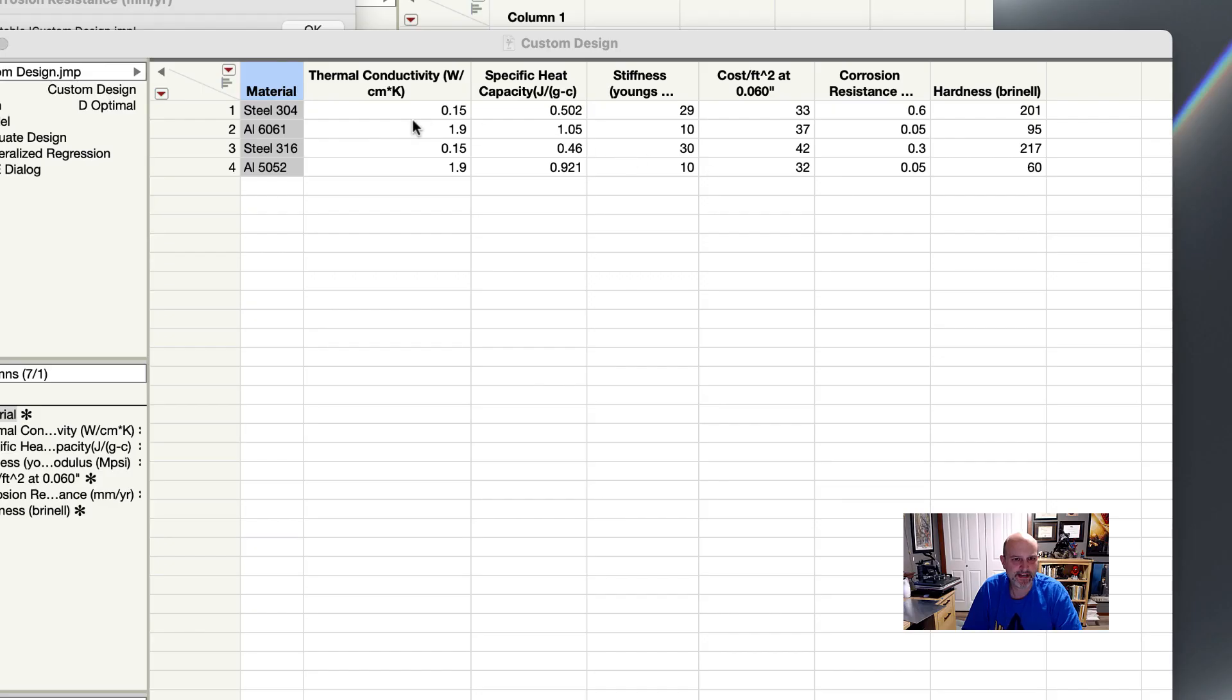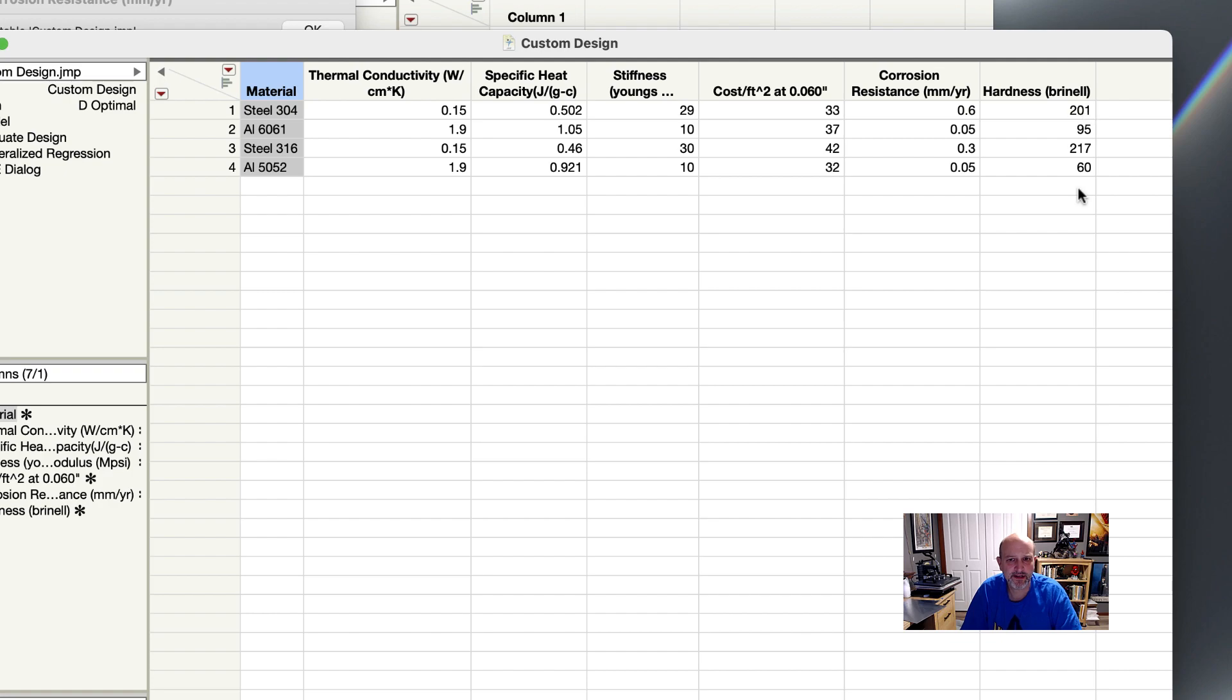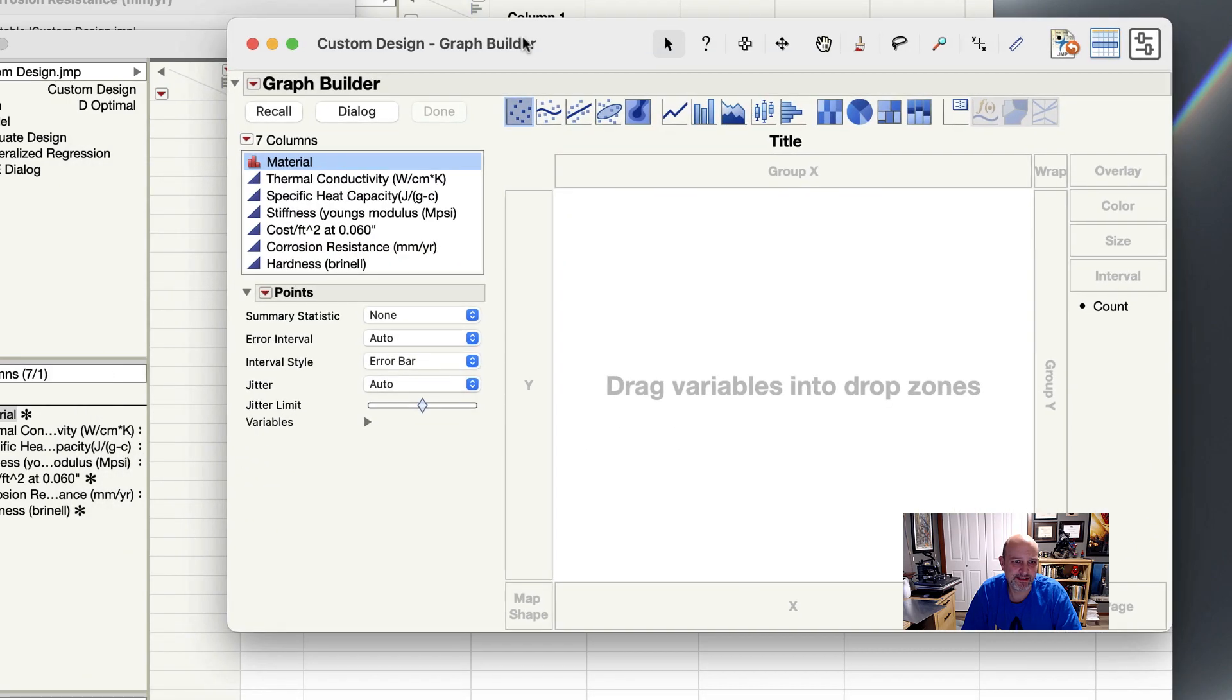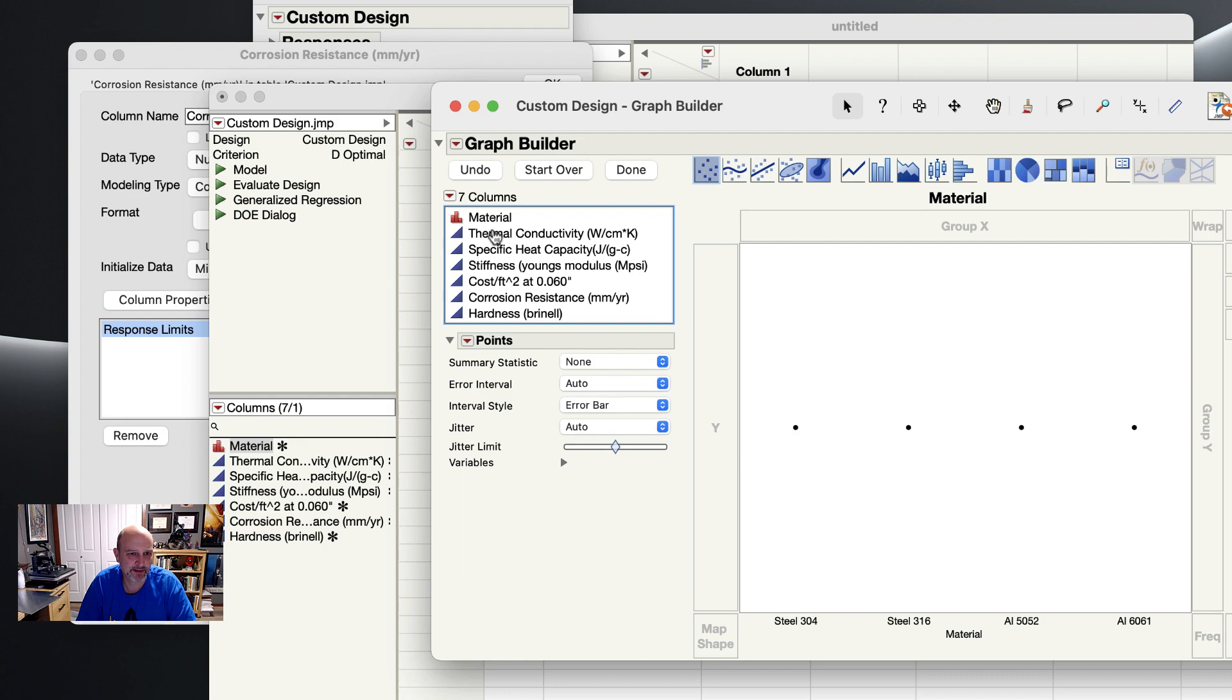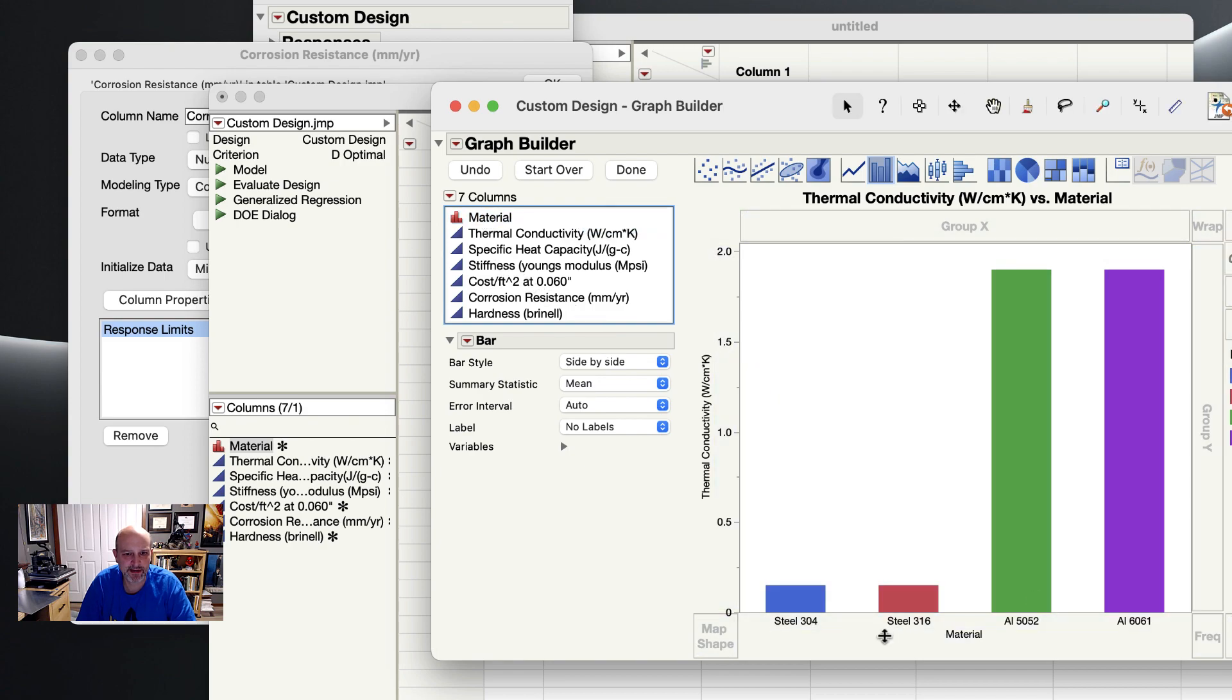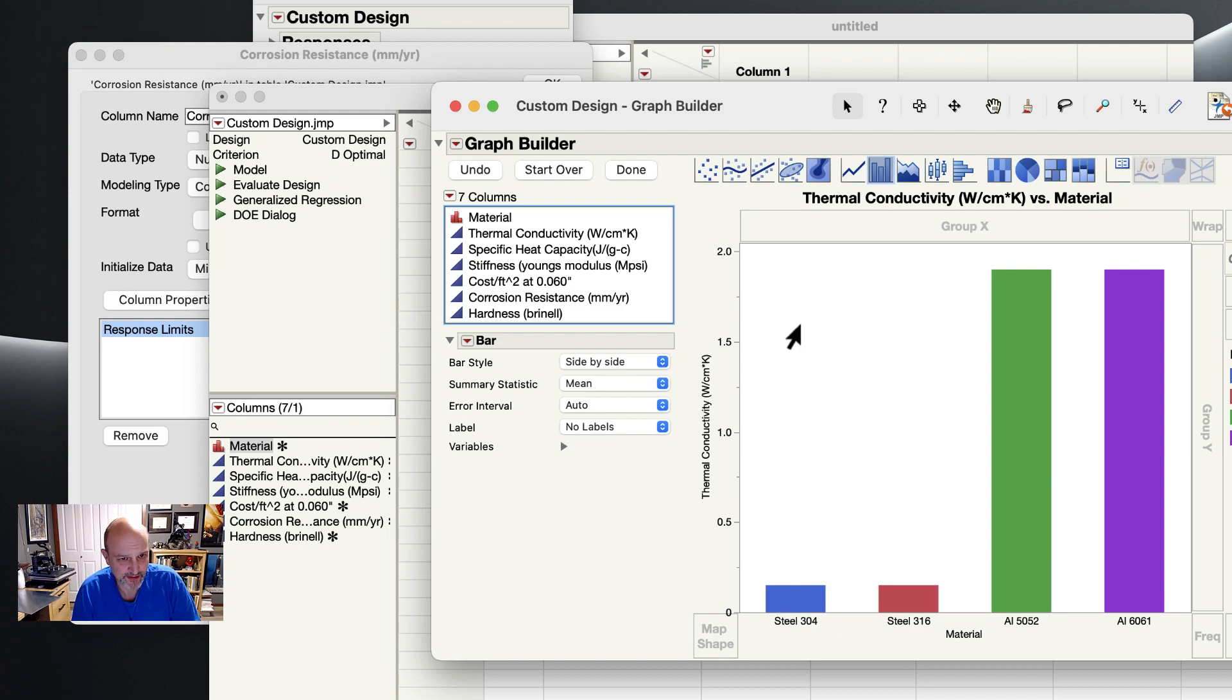So here's our data. I looked this up. Much of it I got in tables, the corrosion data I have because I run a B117 salt fog chamber. I have a corrosion cycling chamber, so I can get the corrosion resistance data in millimeters per year. Everything else, you can also look up yourself. So we have a graph builder. Instead of going over the data in detail, I'm going to just add the material as the x-axis. I'm going to put, I'm going to start with thermal conductivity on the y. I'm going to make this bar graph, and I'm going to drag material to the color to make it more interesting. And you can see when we start, we have the thermal conductivity of the aluminum alloys are way higher than those of the steel, the stainless steels.